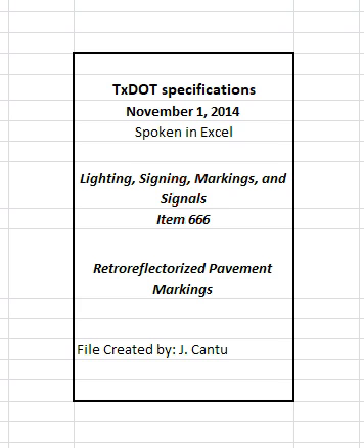The maximum thickness for Type 1 non-profile markings is 0.180 inches, 180 mils. Measure thickness for markings in accordance with Tex-854-B using the tape method.